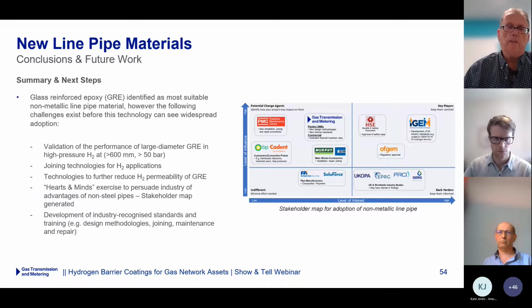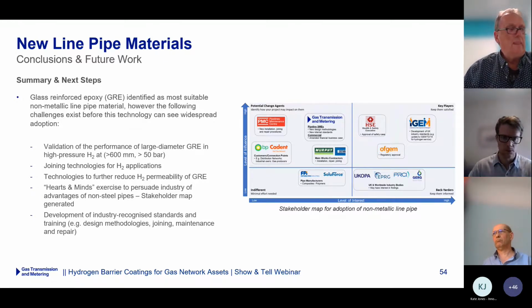Of course, because these pipes are made in sections of about 10 to 12 meters length, the weakness of the whole piping system will probably be in the joining technology, because the system is only as good as its joints. And there are still quite a few unknown factors in terms of the permeability at the joint, but especially in how this is done in the field, because this is done by adhesive bonding. Joining technology in steel pipes is very established, welding, and the welders that work in this industry are probably some of the most skilled and qualified welders available.